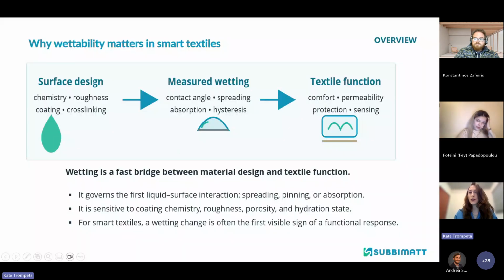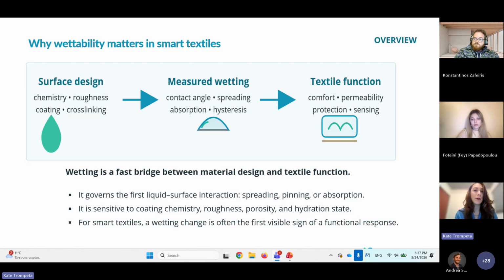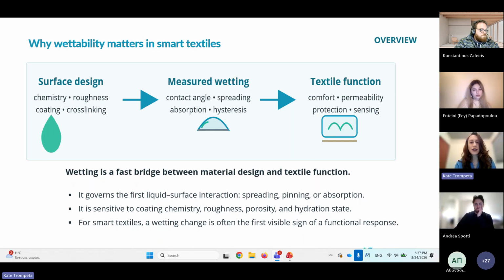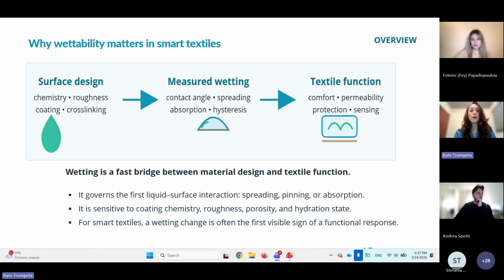I will now have a look at the wettability testing that we do inside the SUBBIMATT project. So why does wettability matter in smart textiles? Wetting is a fast bridge between material design and textile function. It governs the first liquid-surface interaction, so we are talking about spreading, pinning, or absorption. It is sensitive to coating chemistry, to the roughness of the textile and the coating, to porosity, and to the hydration state.